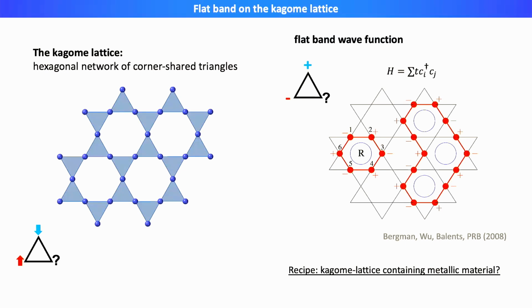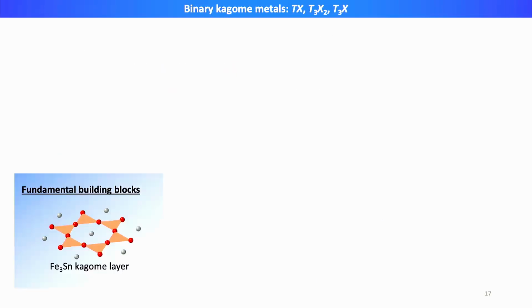So one question you might have by looking at this lattice itself is that there seems to be a huge void in the middle of these hexagons, right? So it doesn't look energetically stable. So how are we able to stabilize this kagome lattice itself? The way of going around this is to put a second element into the middle of the large void space.